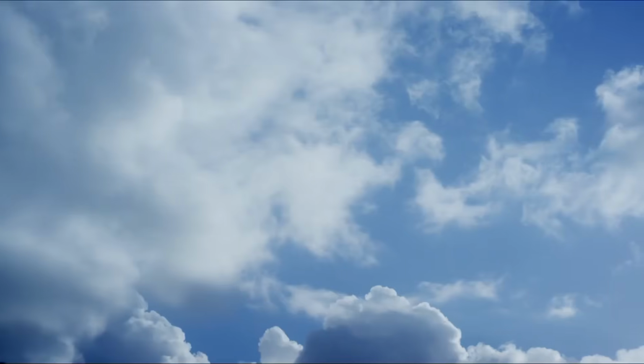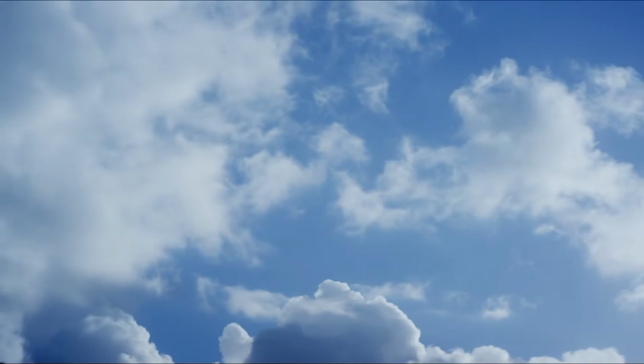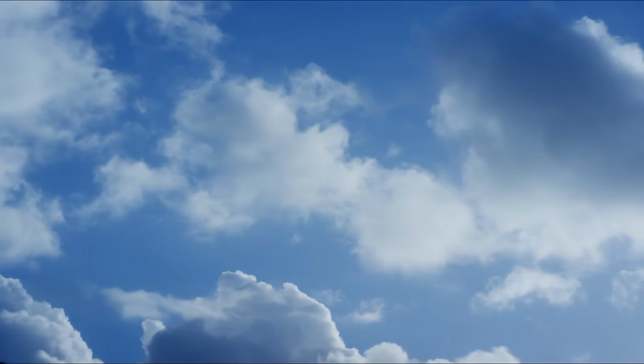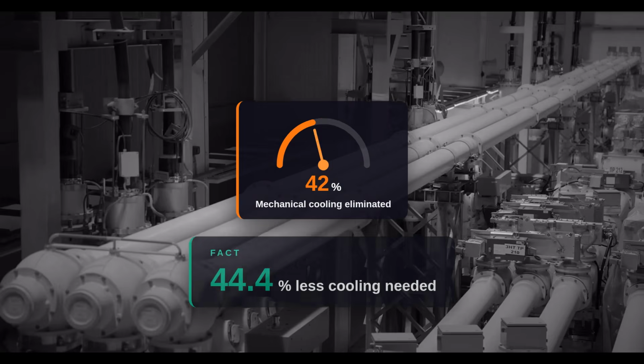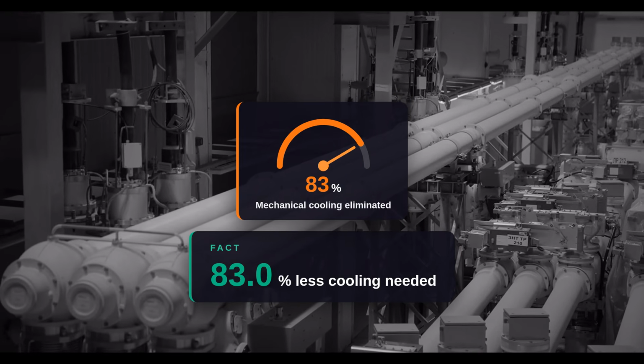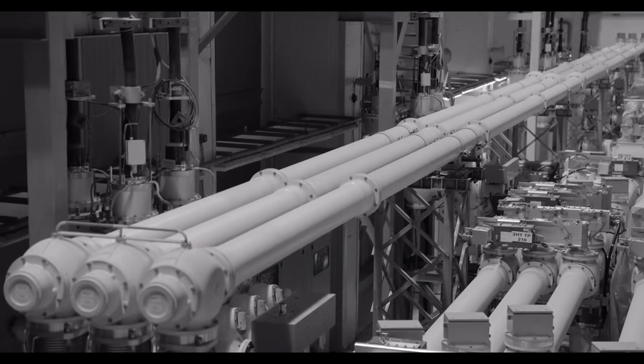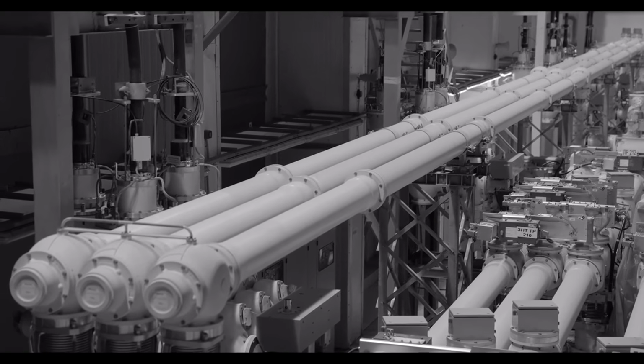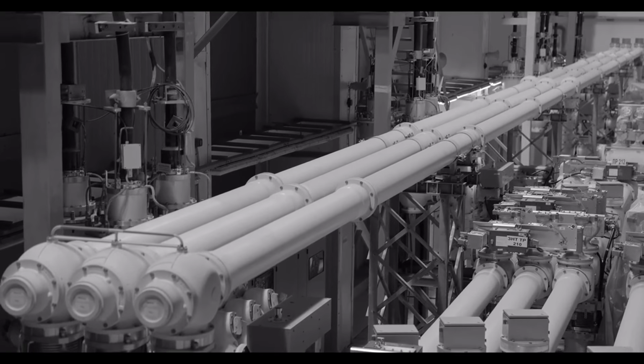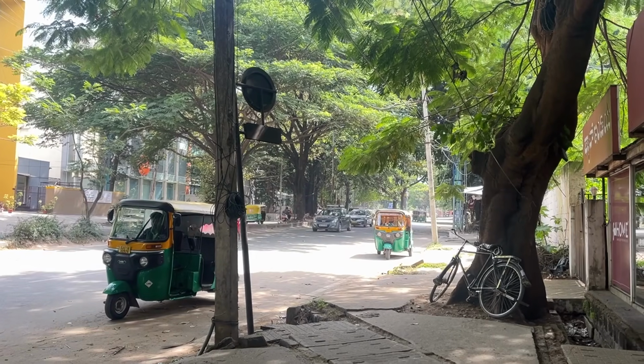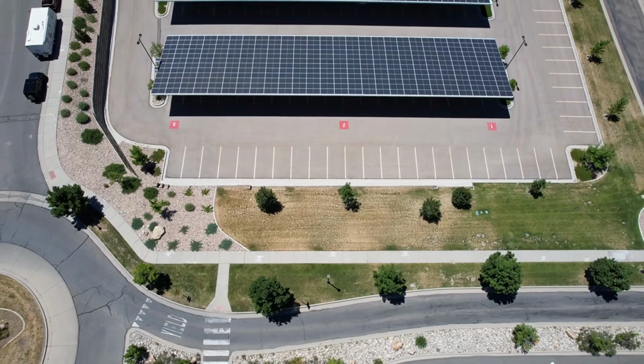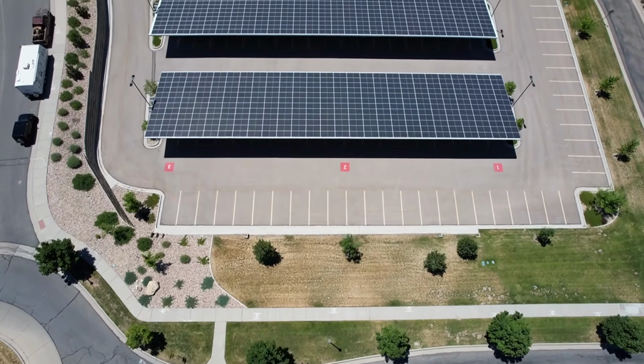In a climate like Bangalore's, where temperatures exceed the comfort threshold for roughly 90 days per year, a building that stays within the comfort range through passive means alone for 75 of those days has reduced its mechanical cooling requirement by 83%. Not improved it, not optimized it, reduced it by 83%. That changes the scale of the system you need to buy, the electricity contract you need to sign, and the carbon you're responsible for over the life of the building.